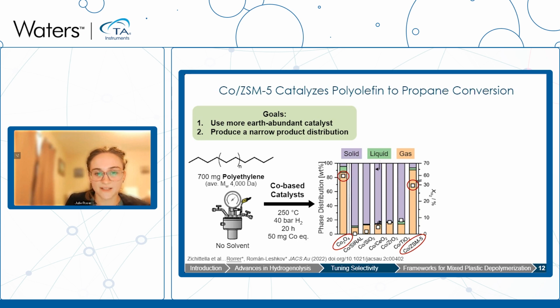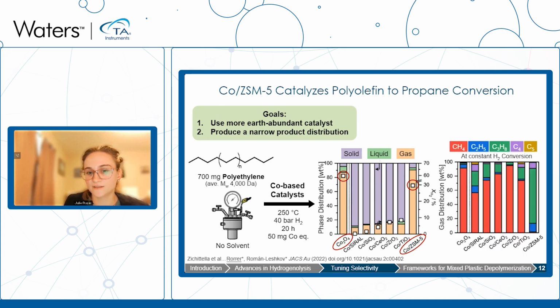Here I'm showing you the phase distribution of solid, liquid, and gas. So we see that the majority of the products here are gas, and our hydrogen conversion over these, which is a metric for activity, is fairly high. And if we actually look at the product distribution of the gas phase, we can see that across all of the catalysts, we see this red bar, which is methane formation. So we're predominantly making methane, with the exception of the cobalt ZSM5 catalyst, which is selectively making propane, a C3 alkane. And this is very exciting because we are creating a more valuable product with high gas phase selectivity.